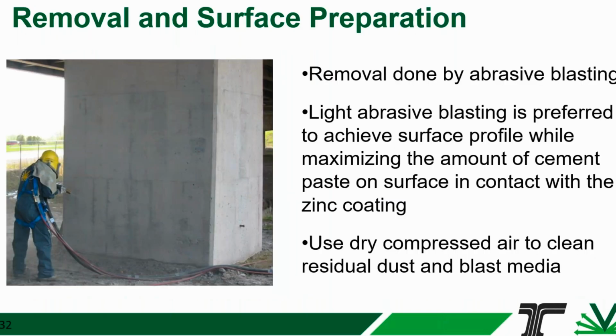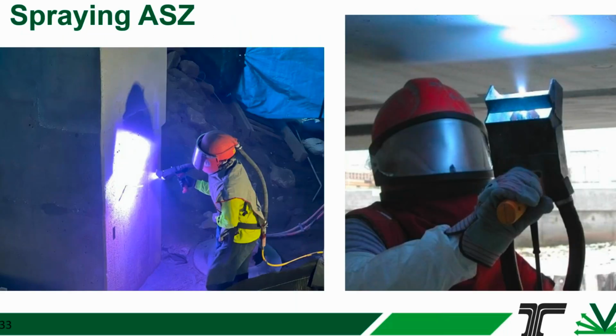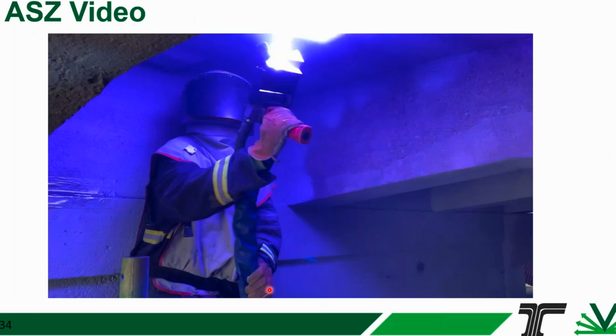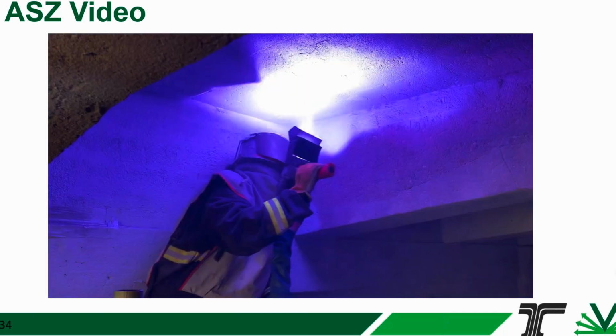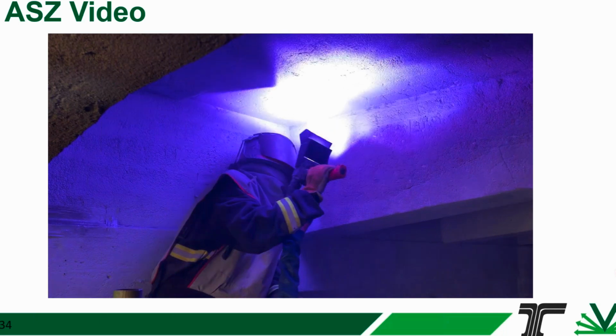And then once the surface is prepared, the zinc is sprayed onto the surface, and hopefully you're going to be able to see this little video showing arc spray being sprayed. Now, when we did the trial before this webinar, for some reason the audio is not playing there, but it's like spray painting, but it's a very loud combination between blowing with compressed air and a small engine kind of running sound. It's a little bit of a noisy process, and you should definitely wear hearing protection. So hopefully you could see that spray application.